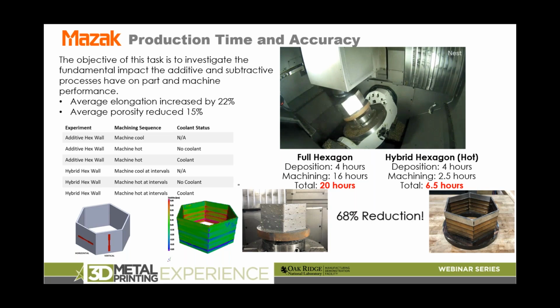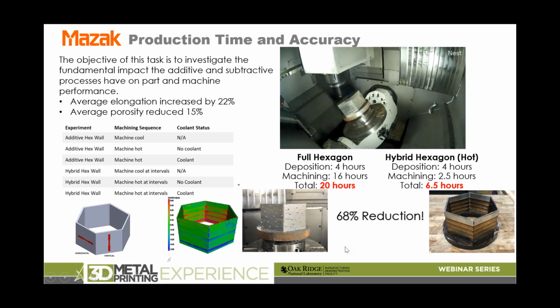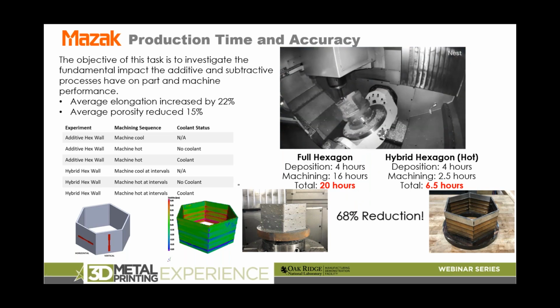What we found was that when we did just an additive process followed by subtractive in that sequential manner, this operation took 20 hours. Well, if we did true hybrid, where we're making some and machining some, we reduced that to 6.5 hours. So you can see the two different parts there. We also see some differences in properties with this versus traditional machining. But anyway, it's a very interesting study to show just the exact advantage of doing hybrid machining.